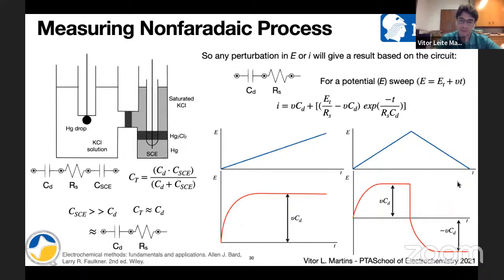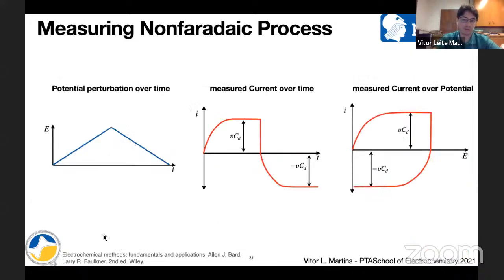So you know that this profile is very well known in electrochemistry. So we have a potential perturbation over time. So you have a measured current over time. And if you plot this measured current over potential, then we have the cyclic voltammogram, right? So we are applying a potential and measuring a current. And this is the kind of profile that we will obtain from a circuit that has only non-Faradaic process or the charging of the double layer.